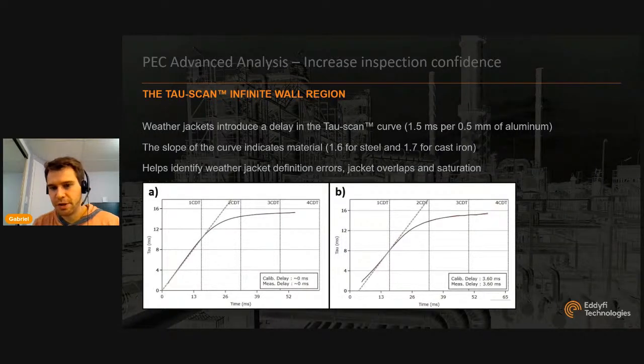So the infinite wall region, this is the first part of the Tau-scan, and that's going to provide you information on the weather jacket as well as the material. What we mean by the effect that the weather jacket is going to have is that typically aluminum, for example, is going to introduce a delay in the signal. So if you introduce an aluminum weather jacket over a component that didn't have one, you'll see that whole Tau scan curve shift to the right. So the shape of the A-scan curve is going to be similar. You might see some effect right at the beginning, that's going to be early in time. But most importantly, you get a shift to the right.